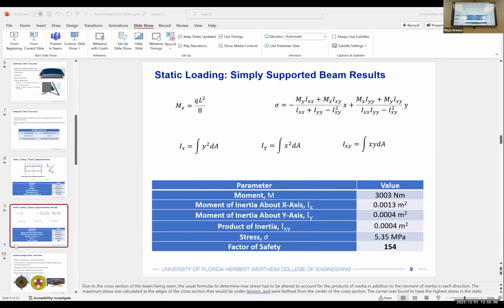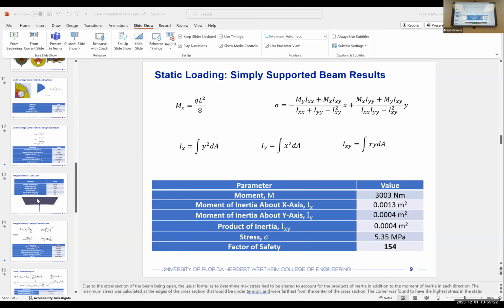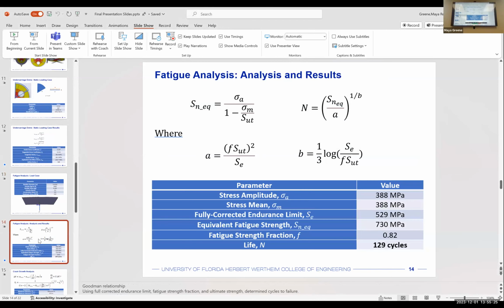I want to say that there's some mistake for the evaluation. So can you change the fatigue analysis? I think there's some mistake there. For the fatigue analysis, the only way you can use the equation is when the fatigue cycle is between 10 to the third to 10 to the 6. That is the stable propagation phase, and that is the equation to model that phase. Below 1,000 cycles, we cannot really use this equation. So when you get a life cycle of 129, it's not really in the region that we can use this fatigue equation.